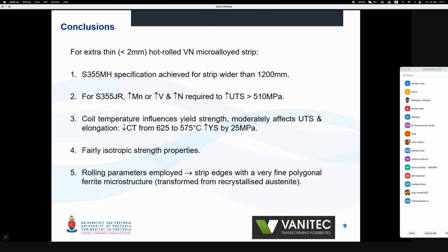And if we want to go to a tougher material, it won't be now for strip, but if you needed to go to an S355JR, you would unfortunately need to increase the manganese or the vanadium and nitrogen, as per that equation that I showed you, in order to get the minimum UTS up to above 510 MPa. That was an original goal, but we found that we weren't going to quite make it, so we had to go back down to the S355MH.